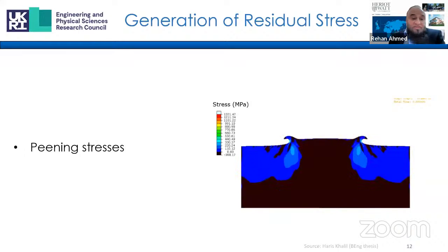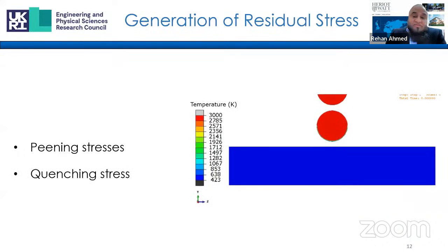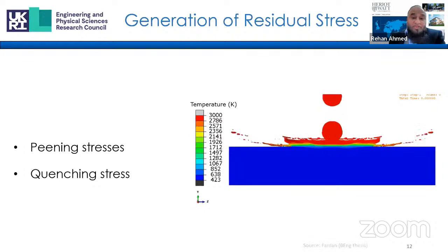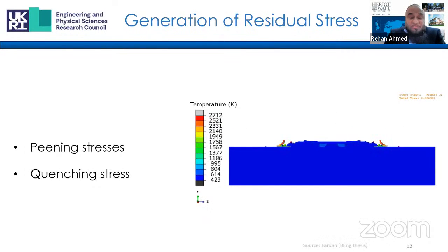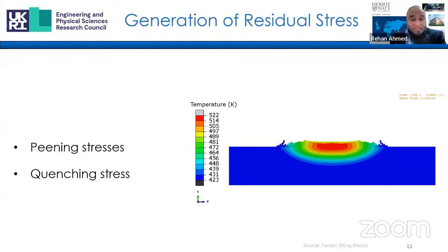Quenching stress is caused due to the contraction of the impacted particle or lamella, and when its contraction is constrained by the underlying material or lamella. So quenching stresses are always tensile due to the restricted contraction. And in this slide, you can see that the temperature cools from high temperature to low temperature. The quenching stresses will eventually develop in the splat, and then as the coating builds up, basically.